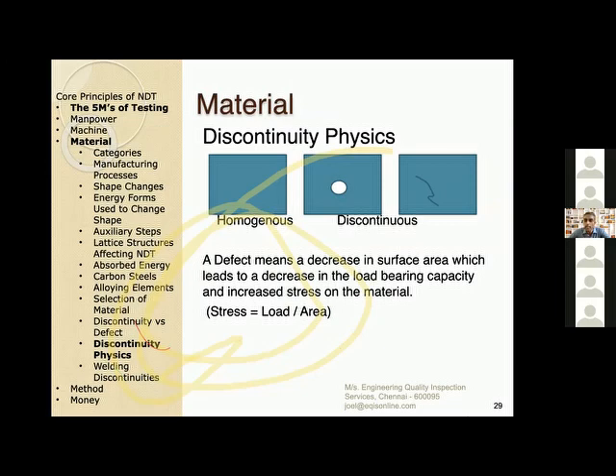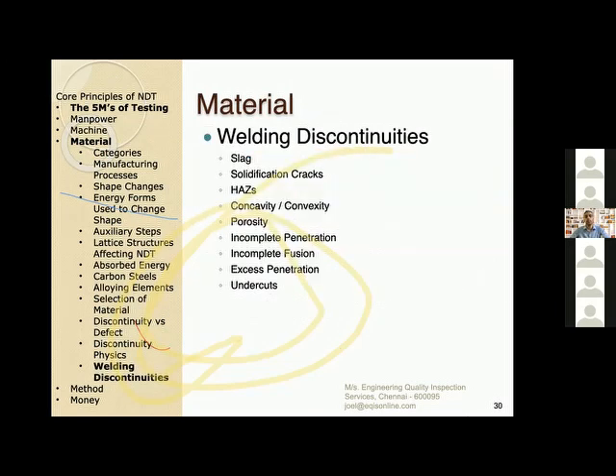So if there is a crack in the metal and I'm going to give a stress, the tip of the crack is going to propagate because it is going to have stress at infinity. So this is why cracks are considered a very, very severe defect compared to a round or a spherical shaped or uniform shaped defect, because this kind of a defect will stay dormant for most of the time and it has smooth edges which will not propagate. Whereas here, since it has sharp edges, one small impact, the crack will grow. Another impact, the crack will grow again. So this is why cracks are considered very important when we talk about